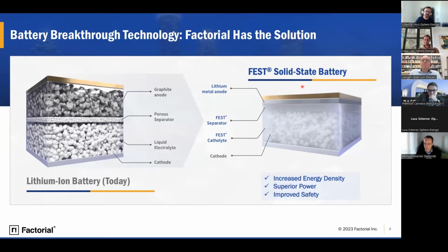So we not only replace the electrolyte, but we also replace the anode part. And I think this picture shows very graphically what this does. So it reduces the overall necessary space for the same energy to a smaller volume. So the graphite anode is, of course, much bigger in volume than the respective lithium metal anode. The cathode in our case remains essentially the same, so very much unchanged. And this yields a system which has not only a higher energy density, but also very good power and presumably higher safety.